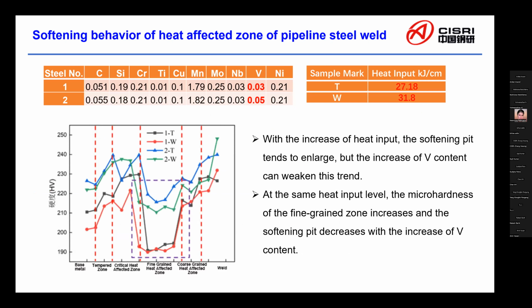At the same time, we have done some weld thermal simulation experiment to study the change of hardness of weld heat affected zone with different heat input. We can see in the picture with the increase of heat input, the softening zone tends to enlarge, but the increase of vanadium content can weaken this trend.